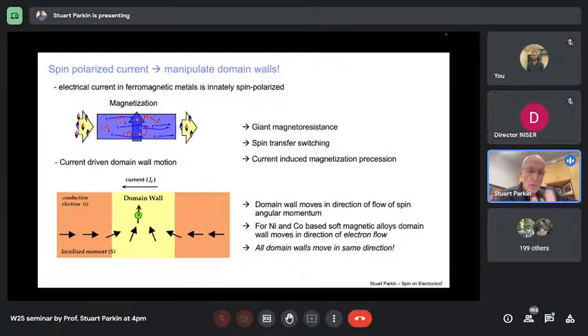And the essential principle is that of the Mott concept, that if you pass a current into a magnetic material, the current is spin polarized. And then the angular momentum of the conduction electrons, as shown in this cartoon, can be transferred from the conduction electron to a magnetic moment in the domain wall. And approximately 1 electron per magnetic moment is needed to rotate that magnetic moment. Therefore, if we have a big enough current, we can rotate sufficient numbers of moments that the domain will move. And in principle, because here you can see the polarization of the electron current is determined by the local magnetization, this should mean all the domain walls will move in the same direction.